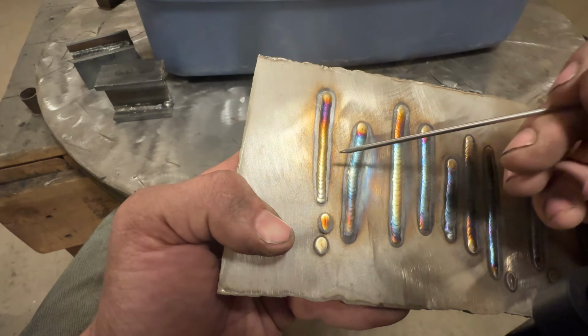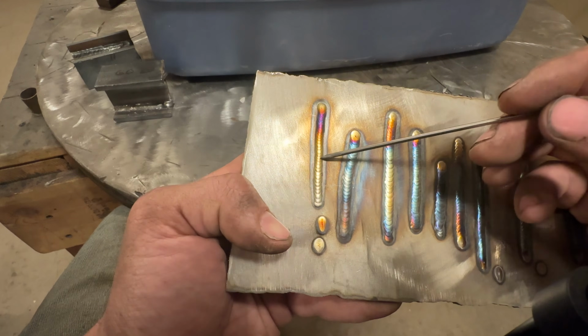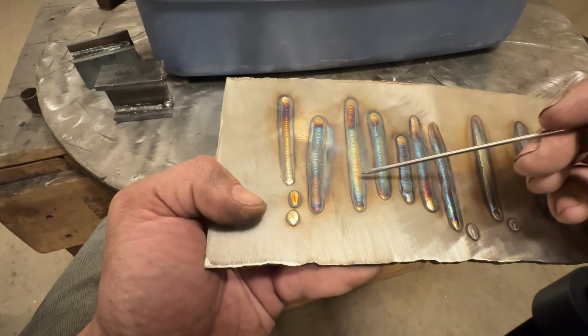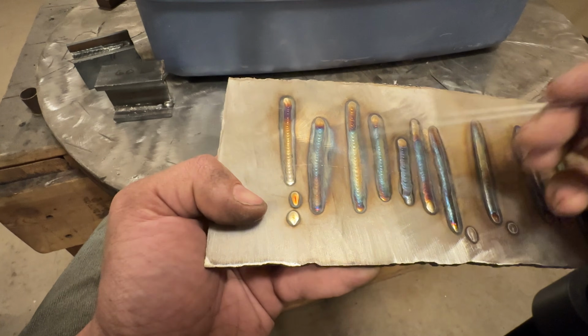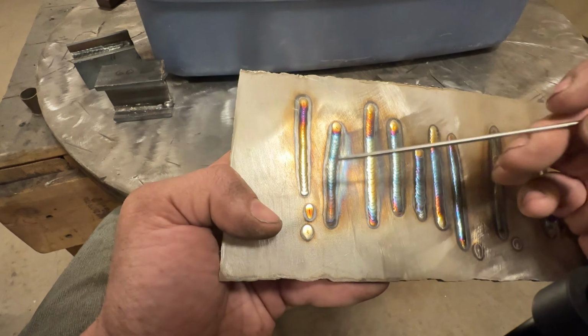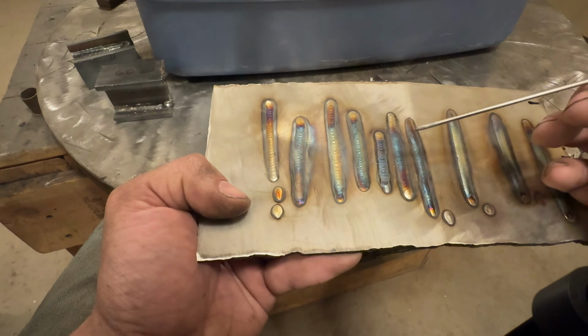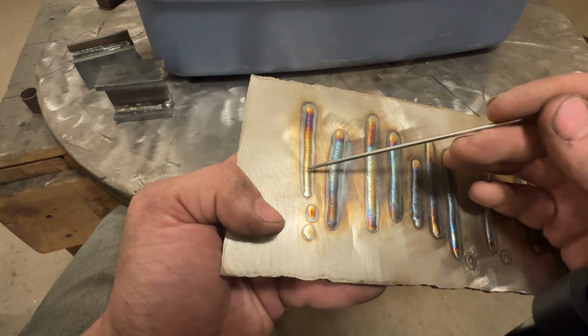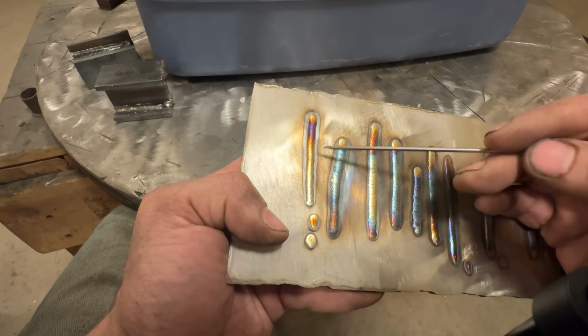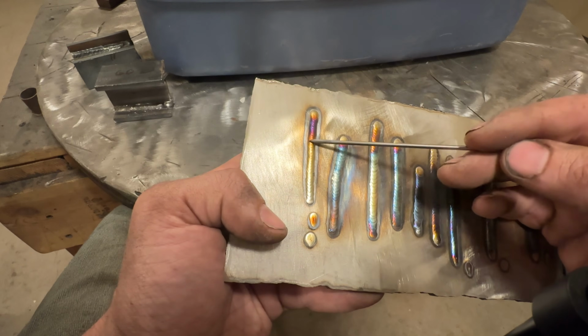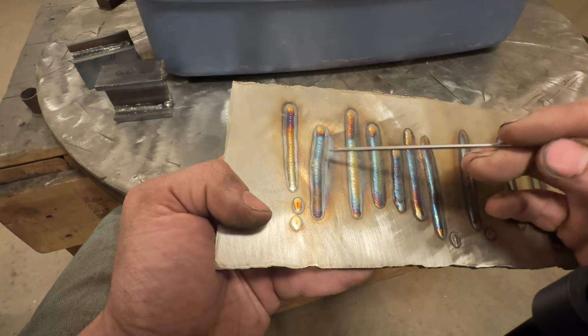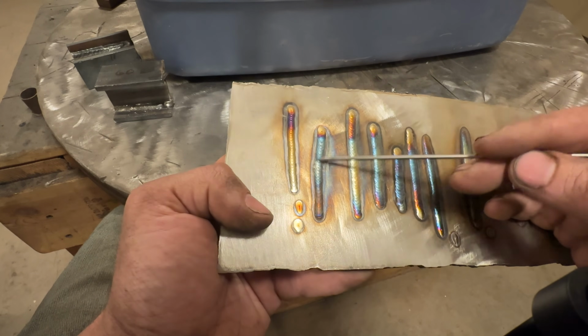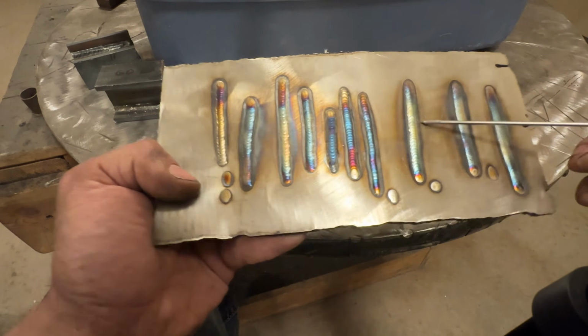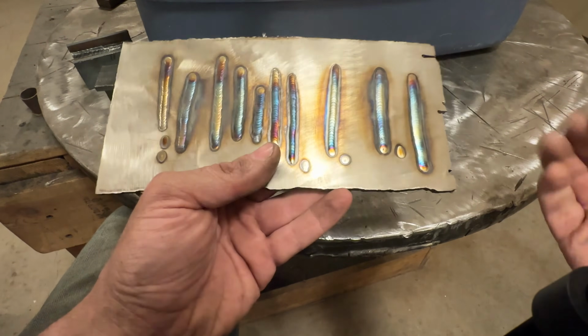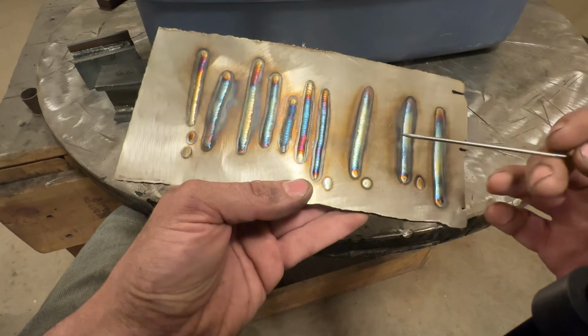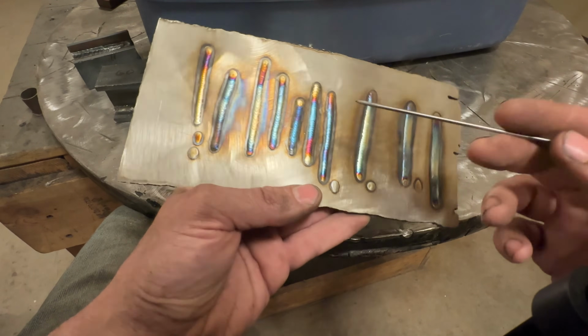In the real world, it's extremely difficult to achieve that because it has to do with the temperature that the stainless is, that the weld you deposited is, when it's exposed to oxygen. At any amount of heat, it tends to turn yellow or straw first, then reds like you see here, then a purplish, then blue, then light blue, like this is light blue, then no color like this, and then it goes dull gray. Now it all depends on what you're welding. If this was food grade, most of these would be unacceptable for the oxide.